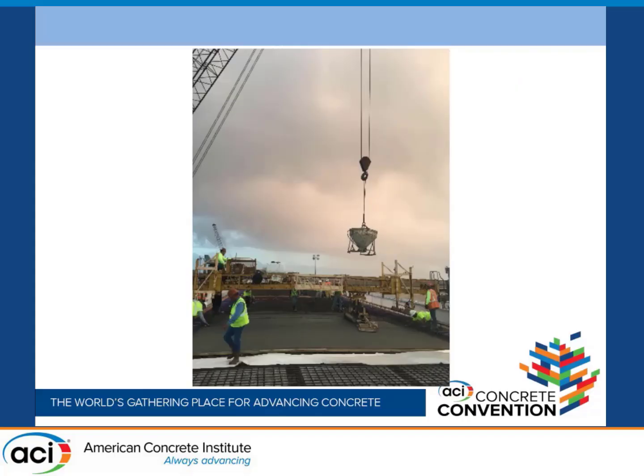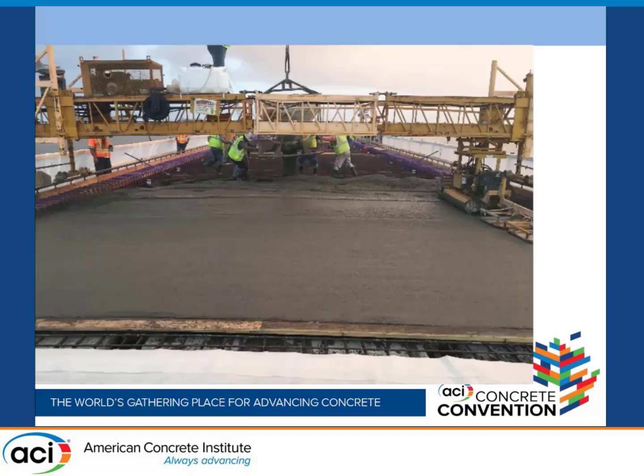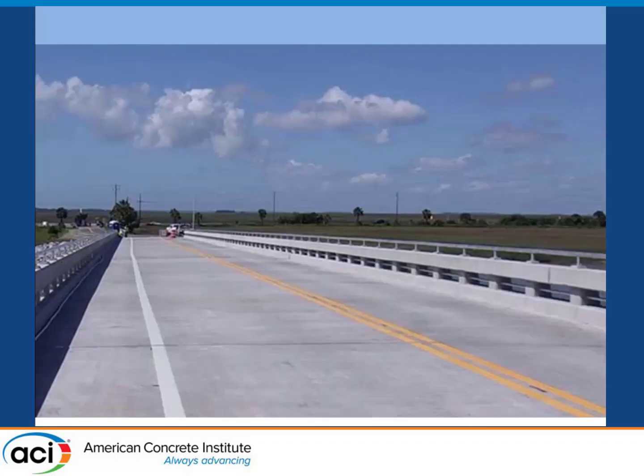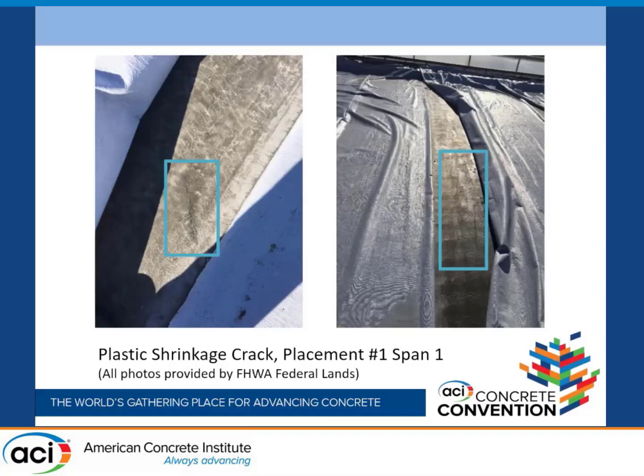So they went back to a 3 cubic yard bucket, and this provided ample production. They were satisfied with their progress. So they did all 13 of the spans on this bridge using a 3 yard bucket, and about 900 yards of internally cured concrete. The new bridge is about 29 feet wide, including the rails, with two 11-foot lanes and a 5-foot shoulder on the downstream side.